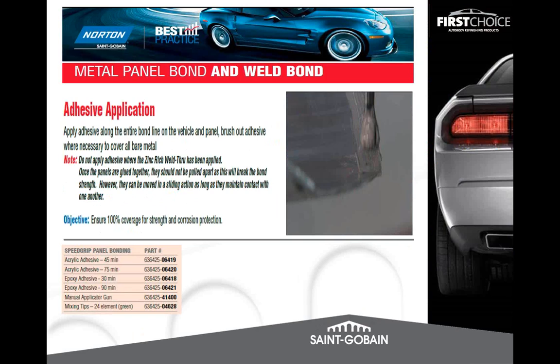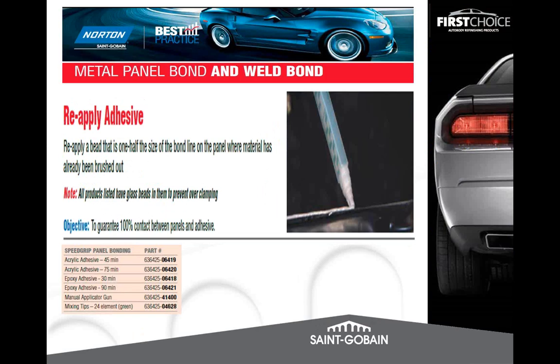So once we apply the adhesive along the bond line, we actually are going to apply another bead of material. And the reason for that is to make sure that we get proper adhesion between the old panel and the substrate, and we actually get some squeeze out or ooze out. This way we know both panels have come in contact. The neat thing about all these adhesives that are listed here, they have what they call glass beads in them, so you cannot over clamp it.